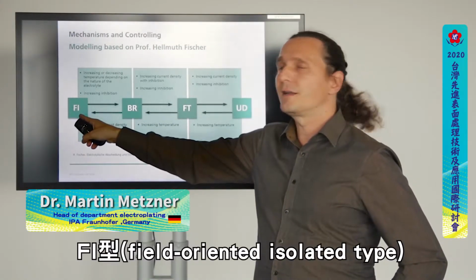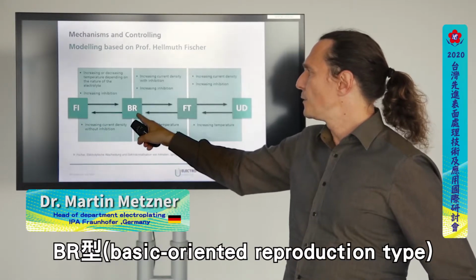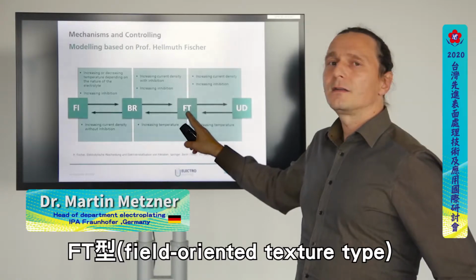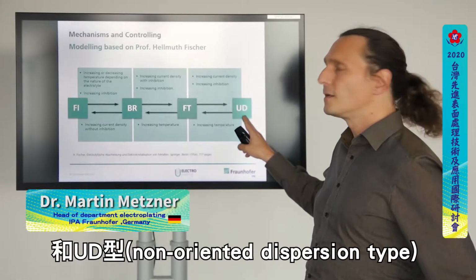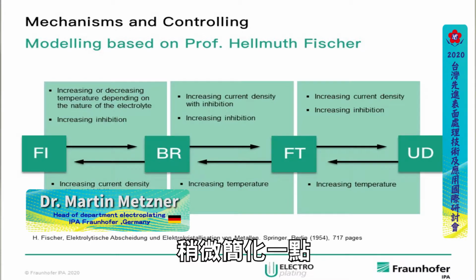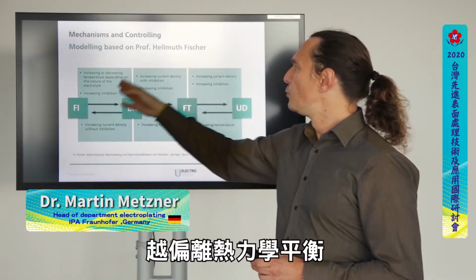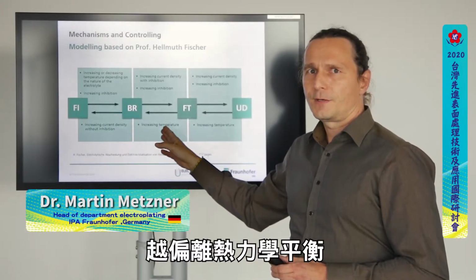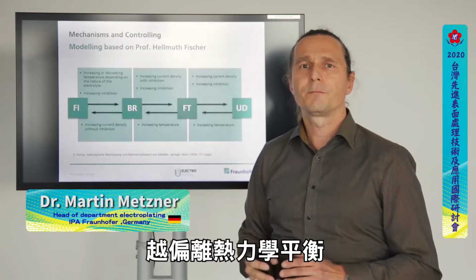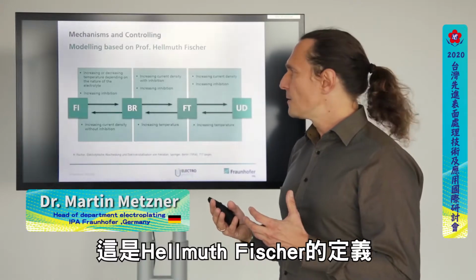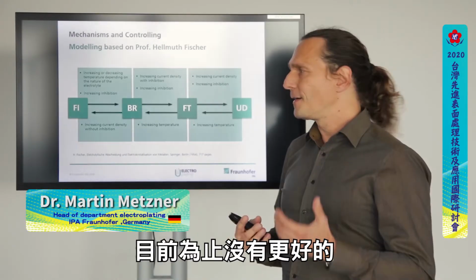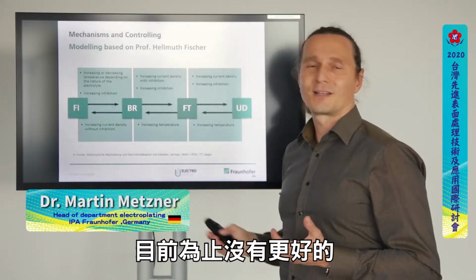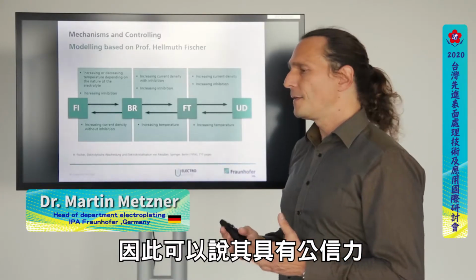It's called field-oriented isolated type, basic-oriented reproduction type, field-oriented texture type, and non-oriented dispersion type. To make it a little bit more simple, from the left to the right, the higher you go, or the farther you go away from the thermodynamic equivalent. Means from here to here, you raise the inhibition, raise the current density, or lower the electrolyte temperature. This is the definition of Helmut Fischer, and there's nothing better that was found out until now. So I think we can really say this is true.